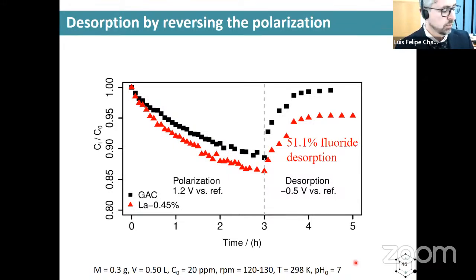Also, we explored the reversibility of the process. This is important, of course, for the regeneration of the material. No? You can see that if we invert the polarization, we provoke the desorption of the fluoride, reaching almost 50% of the fluorine desorption in the case of the modified electrodes. No? So in conclusion, the electroadsorption of fluorine was favorable with a very small amount of lanthanum.